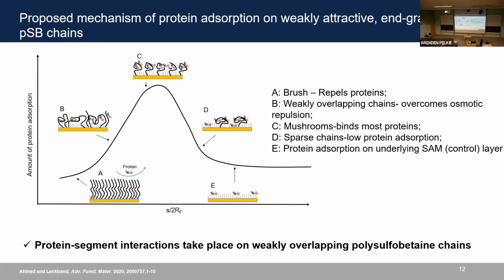And so with lower grafting density, now the interactions increase, and so the amount of protein adsorption increases, reaches the maximum, and then it further goes down because here there are not enough polymer chains on the surface to interact with. And finally, at point E, the adsorption profile plateaus at an amount that is expected on a control substrate, which is OH terminated thiol for our case.